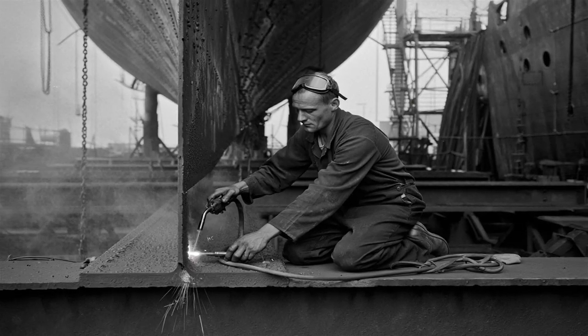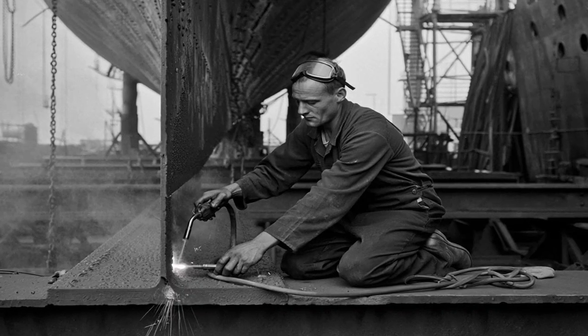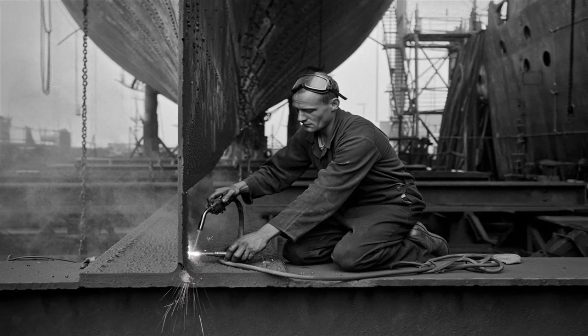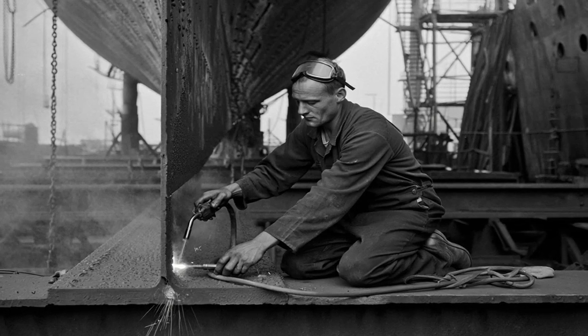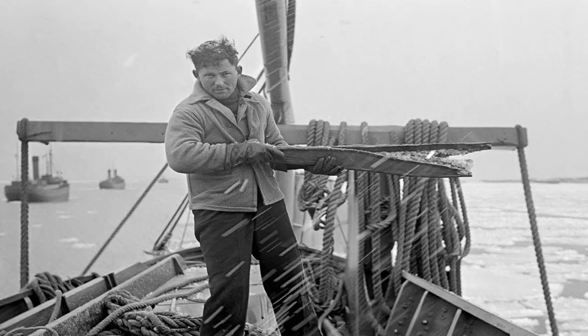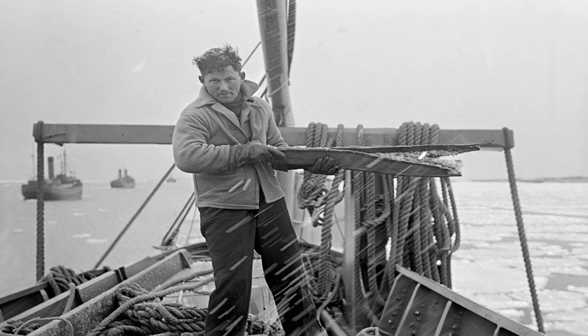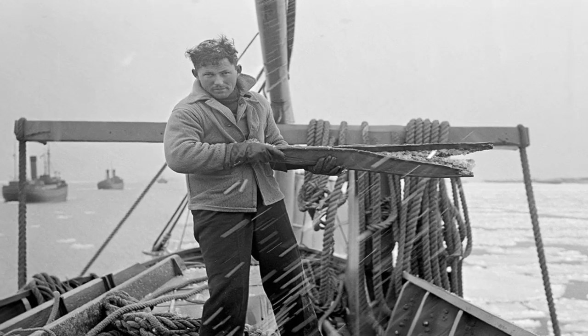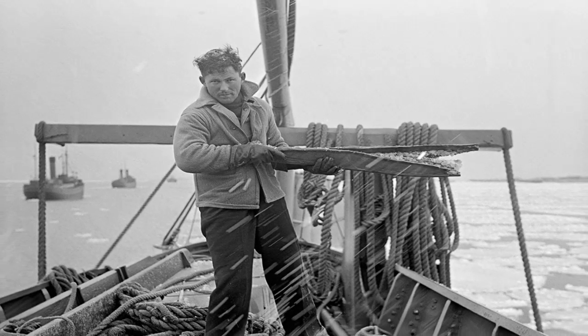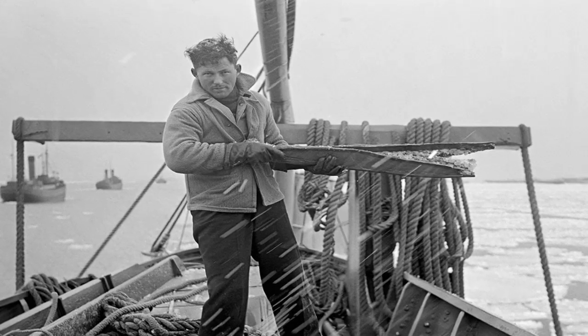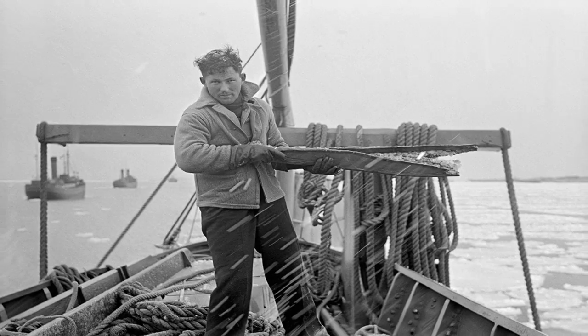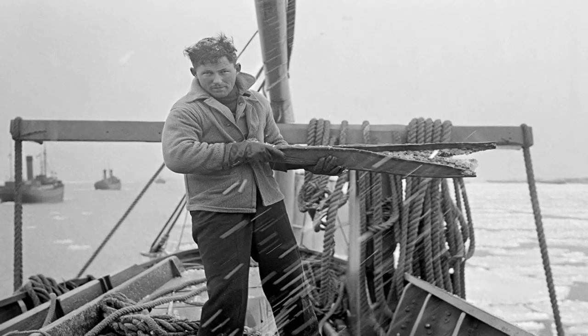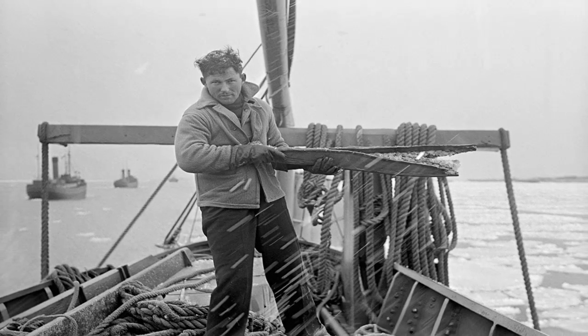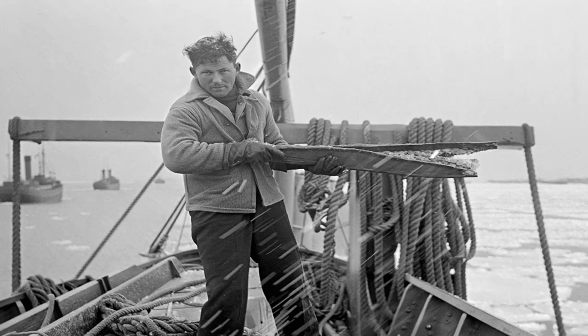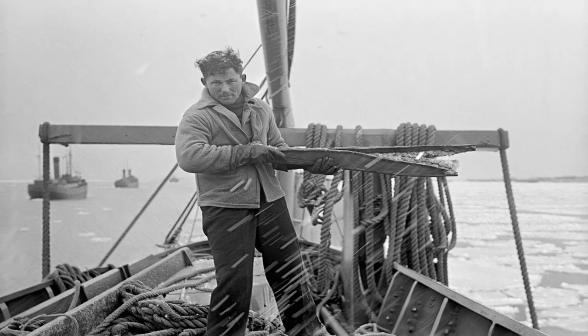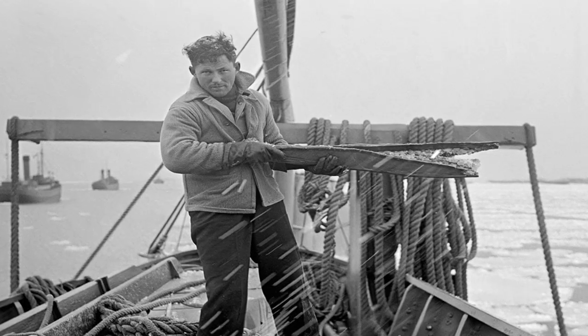Liberty ships were plagued by what specialists term brittle fracture spread. The carbon steel in their exteriors, specified for marine construction, held up fine in temperate seas but shifted perilously in the North Atlantic's sub-zero chill. Under about 40 F, the material's pliability vanished. Typically, alloys handle loads by yielding a bit, flexing instead of snapping. Chilled steel forfeits that resilience. It turns rigid, resembling brittle ceramic more than the resilient stock shaped in California's temperate docks. When such rigid metal encounters focused internal pressures at an acute angle, like the straight rim of a loading port, natural forces assert themselves with ruthless speed.